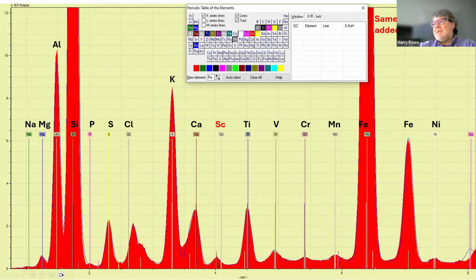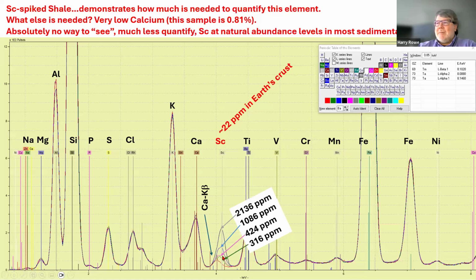What I did was spike this shale with various amounts of scandium oxide. So I spiked it with 2000 ppm scandium. That's what 2000 ppm scandium looks like. By the way, average Earth crust has 22 ppm. So it's buried underneath that calcium peak, all the way down to 316 ppm. So that's over 10 times the amount that we really ought to see in this rock.